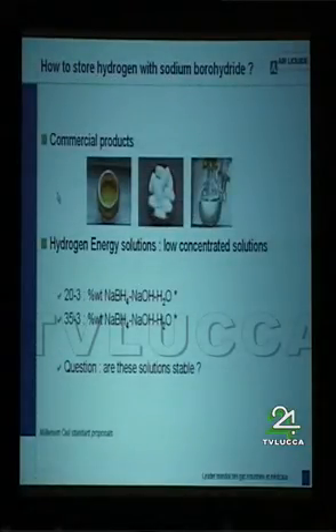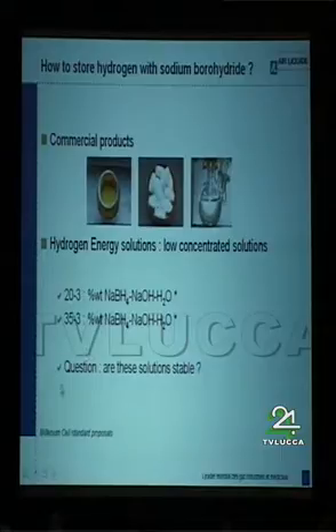So the first question was how to store hydrogen with sodium borohydride. The commercial products are powder, tablets, or liquid. The liquid form is a highly concentrated sodium hydroxide liquid, and it is a very corrosive solution. That's the way to buy sodium borohydride today for fine chemicals. For hydrogen energy solutions, the solutions were low concentrated in NaOH. These are the typical Millennium Cell solutions. It is 20 weight% NaBH4 and 3 weight% NaOH, and then water. The other solution is 35 weight% NaBH4, 3% NaOH, and the rest is water.